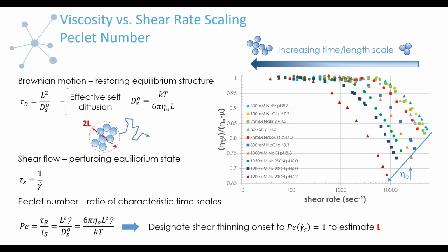So what I've done is subtract off mu, which is the buffer viscosity, and then scale this on the low shear plateau minus the buffer. Ideally, if I was able to get the high shear plateau, I would want to use that rather than the buffer, but unfortunately I don't have that. So this is the next best thing. And this is still plotted versus shear rate in dimensional form.